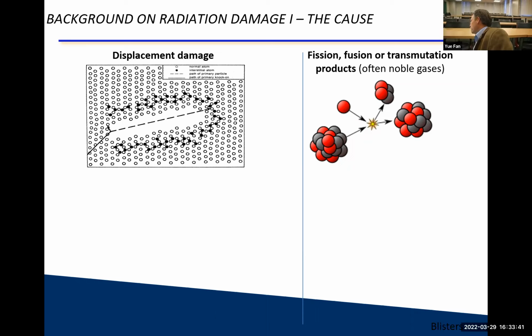Your energetic particle comes in, displaces your atoms, and then you create knock-on cascades, which displace all the other atoms around. Of course, most of those atoms jump back at the end of the day, and you have a sort of perfect lattice. But you had these atoms being displaced, and therefore the dose we characterize in nuclear materials is displacements per atom. So 1 dpa, 1 displacement per atom, means that every atom on average has been displaced 1 time from its original lattice site.